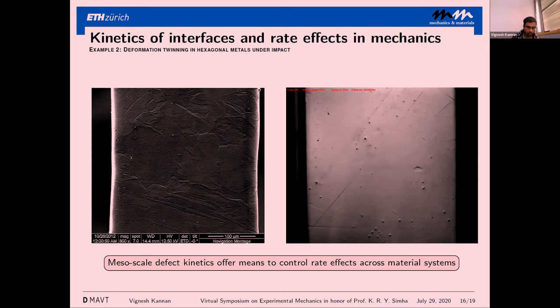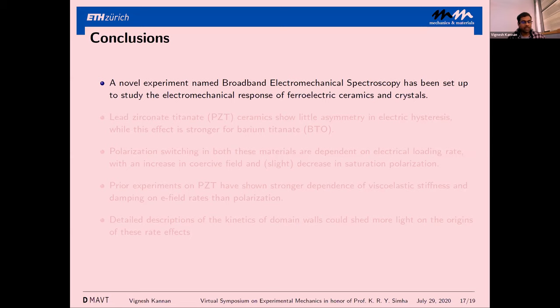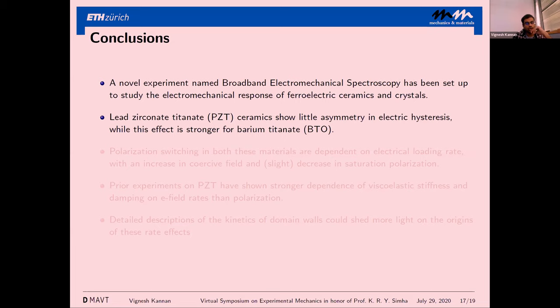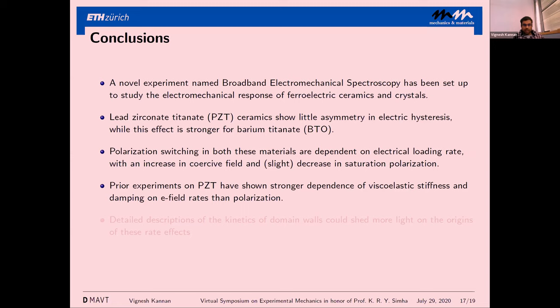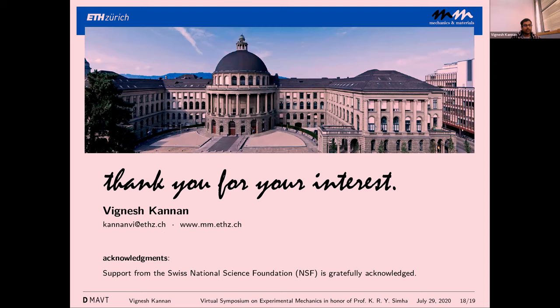In conclusion: we have an experiment — the BES — to study ferroelectric ceramics and crystals. Our first measurements on PZT ceramics show slight asymmetry, much stronger in barium titanate, which we believe is due to texture. Polarization switching in both materials is highly dependent on loading rate: we see an increase in coercive field and a slight decrease in saturation polarization as loading rate increases. Viscoelastic stiffness and damping show strong dependence on electric field rates — even more sensitive than polarization. We are working on hybrid experimental and theoretical methods to describe mesoscale kinetics of domain walls and predict macroscopic rate effects.